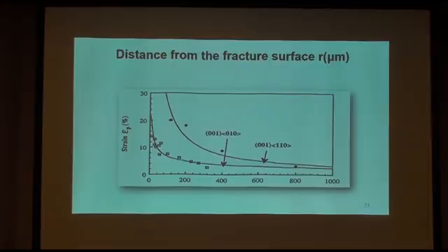This is a very interesting illustration that we are taking two systems and we are trying to follow the crack tip in two systems. One is the 001, the basal plane in the <010> direction, and the other one is the same type of plane and the 110, and we are following the strain that accompanies the extension, and we see down, 200 microns, 400 microns, 600 microns, and so forth.